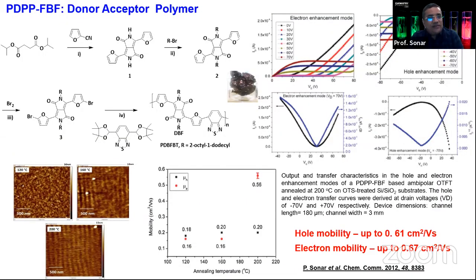And this is another polymer. So we just changed from thiophene to furan, and then we moved to furan DPP. Again, you can see the color of the polymer, then the AFM data, and in this case the mobility values we pushed up to 0.61 centimeter square per volt second for hole and 0.67 for electron. So we are continuously trying to improve these values.